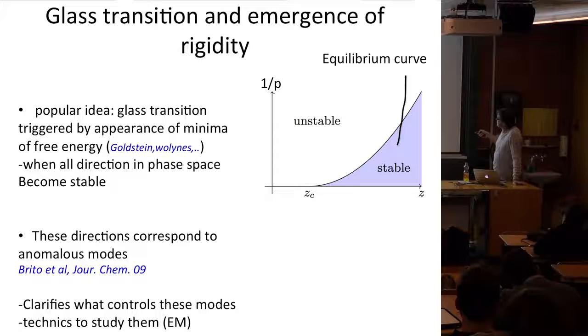And you can also look at this coordination versus pressure relationship. So what it's supporting is that those colloidal hard spheres, so those systems that are bouncing into each other, live again close to the edge of an elastic instability. This effective free energy has directions in phase space that are almost completely flat.